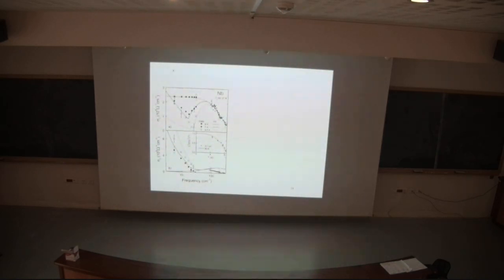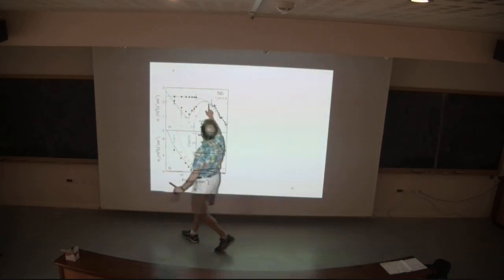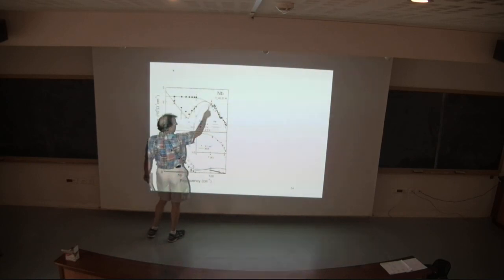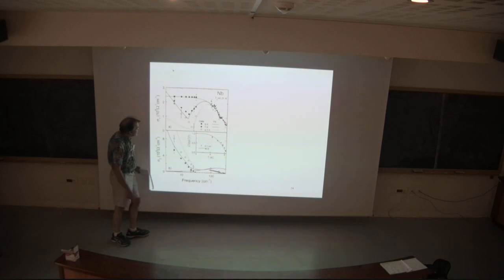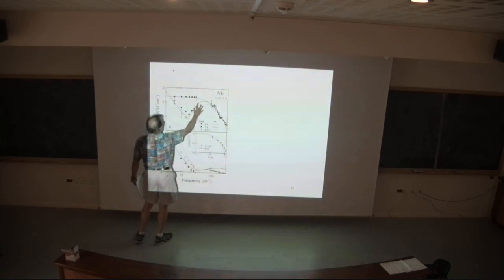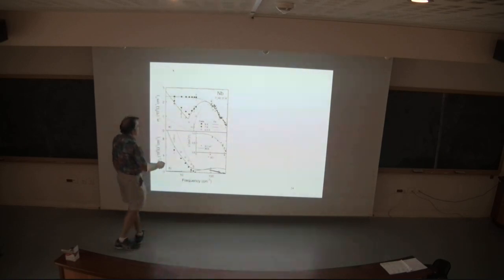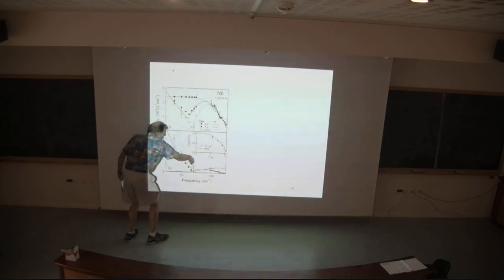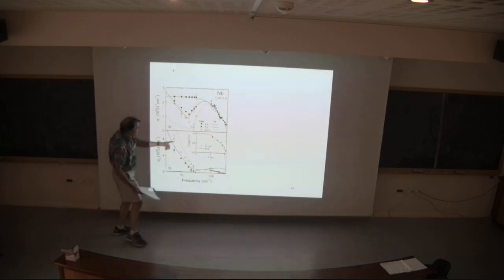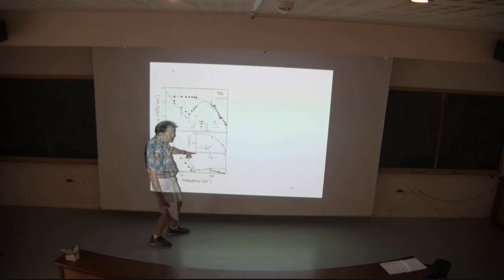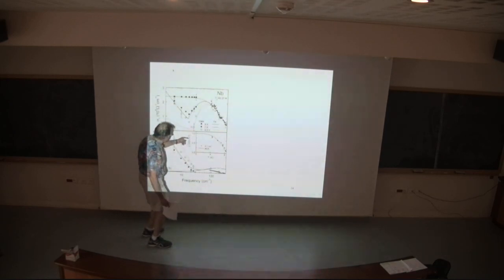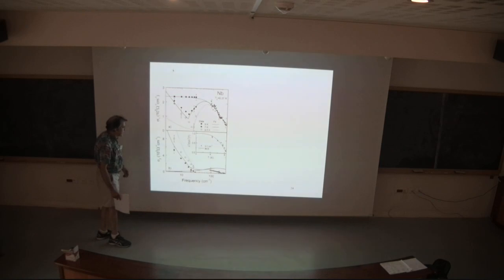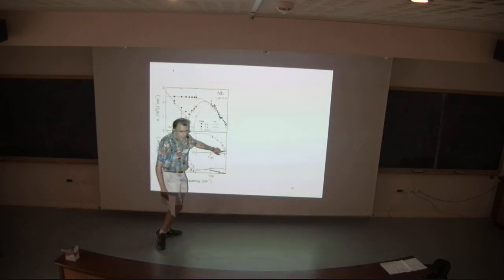Here is niobium, okay? You can measure the optical conductivity either by doing transmission through a thin film or from reflectivity. And here is the Drude behavior of niobium in its normal state. I guess at 9 Kelvin, its Tc is 8.3 Kelvin. And as you cool it down, you see the transfer of spectral weight into a delta function, which you can't even see. But you can see here sigma 2 and this 1 over i omega component developing as it goes superconducting. And here is the penetration depth squared as a function of temperature. This is 1 over lambda squared as a function of temperature. And this part does fit a BCS theory, which we still haven't talked about yet.